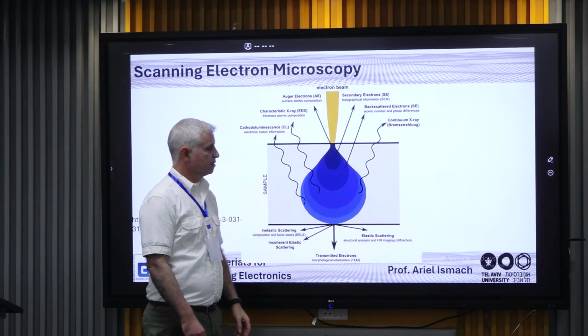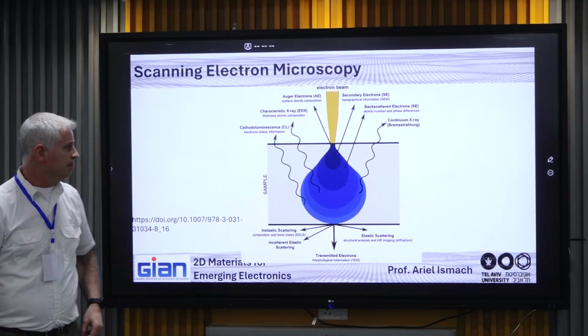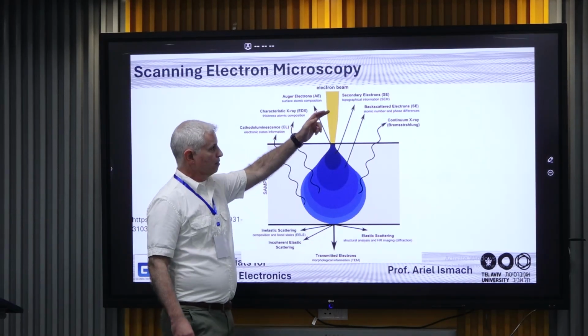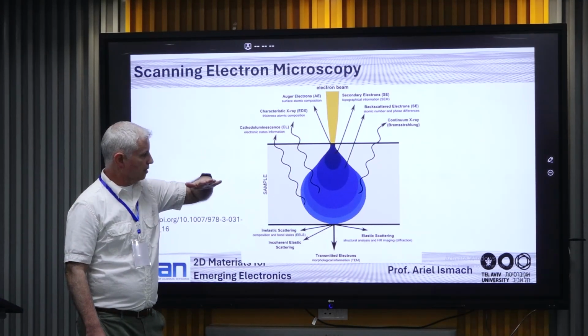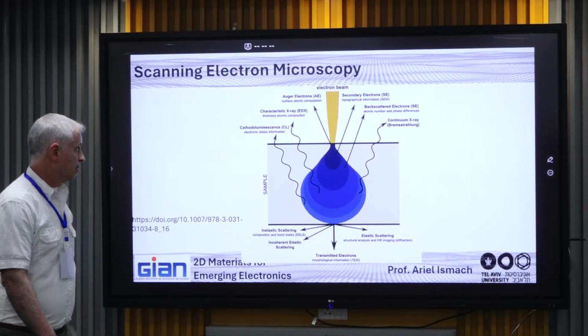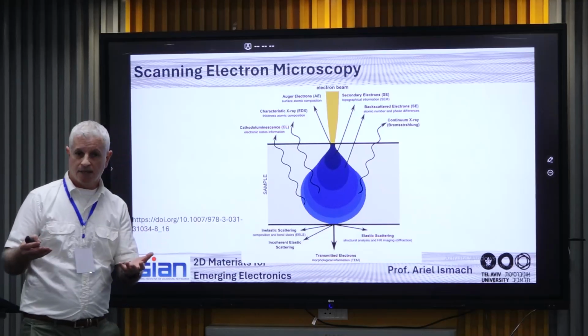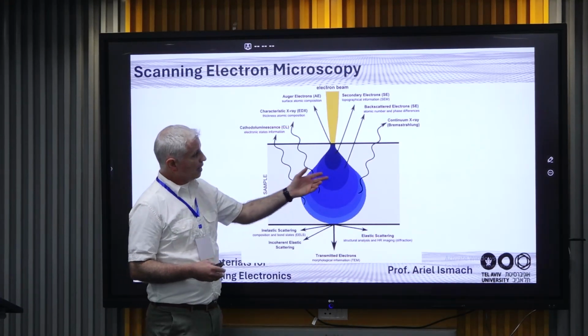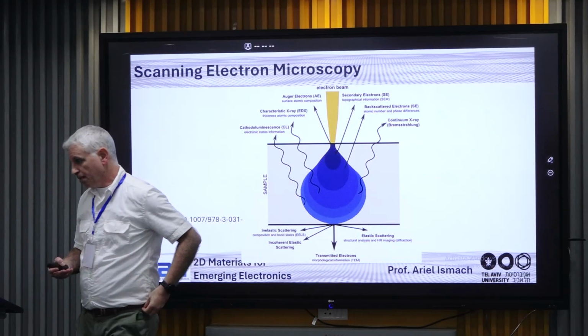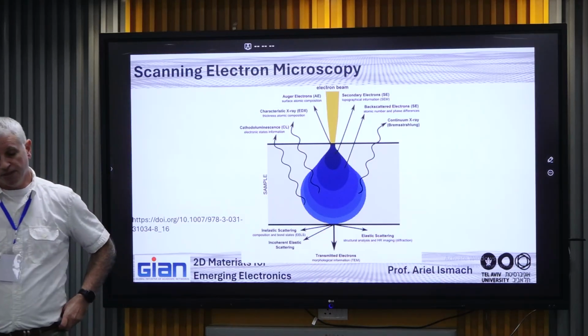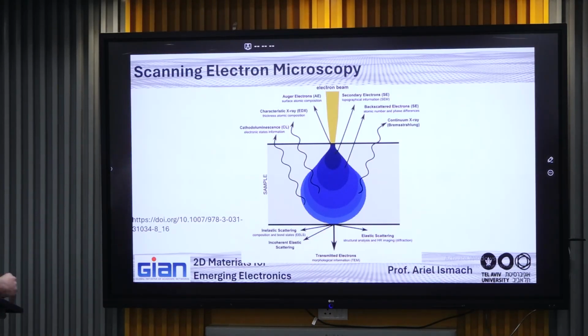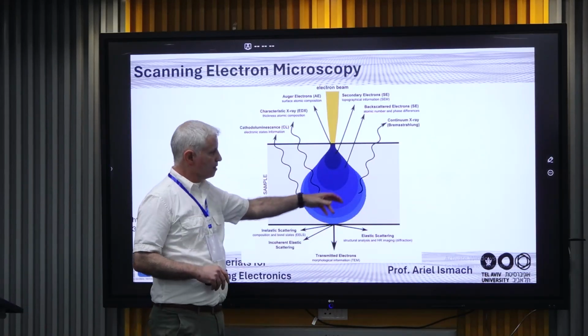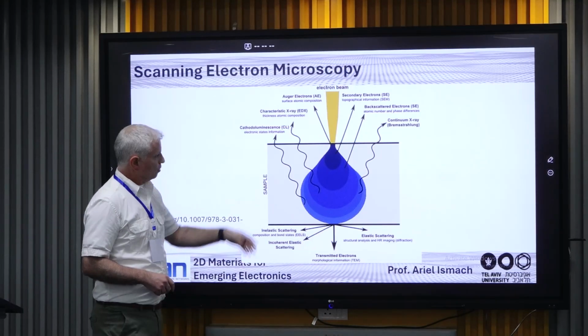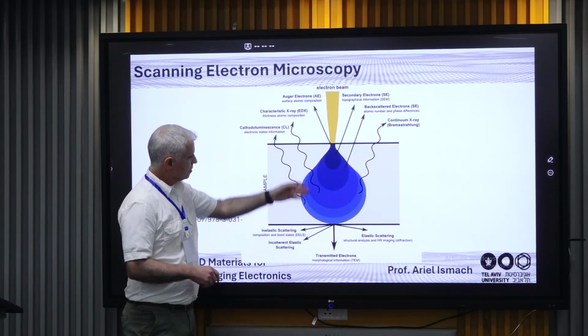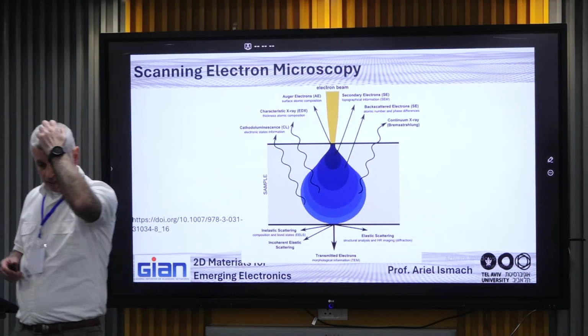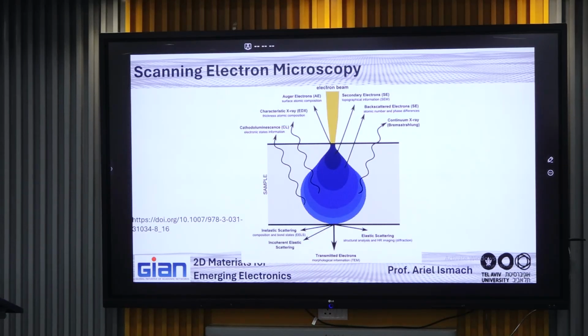you have the backscatter electrons. These are the two main detectors in every SEM. The secondary electron interaction is sensitive to the surface structure and morphology, while the backscatter electrons are sensitive to the atomic number of the atoms. Therefore, it gives you a way to differentiate between different materials. And then from deeper areas, of course, you can get X-rays, cathodoluminescence, and EDX, characteristic X-rays that are useful for elemental and chemical composition.